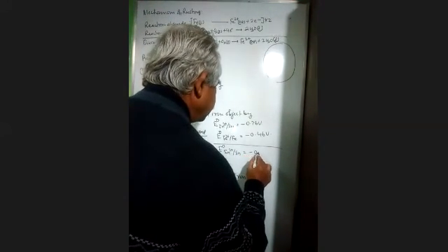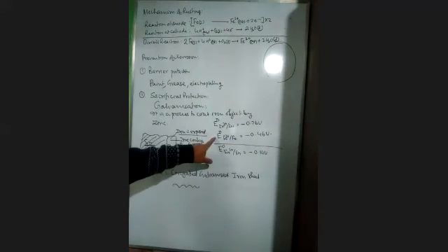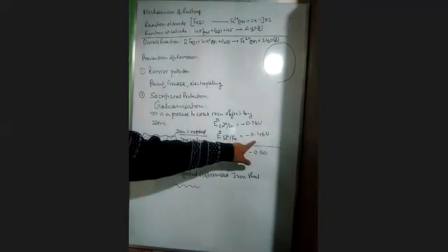It is minus 0.14 volt. So it is lower. So in this case, you find this is made of iron sheet coated with tin. The moment a portion of the tin has fallen, you see here in this case iron gets exposed, and now this acts as an anode. So immediately you find the corrosion or the rusting is going to occur.